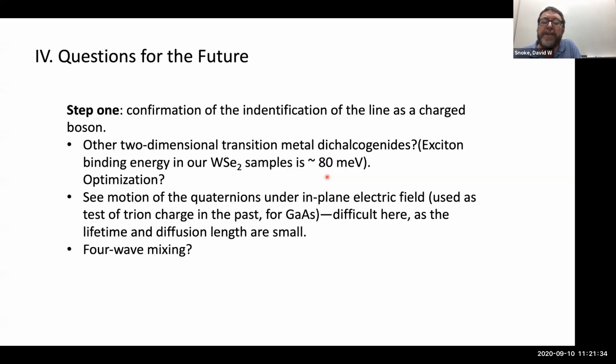A great experiment to do, which is a very difficult one, would be to apply an in-plane field and look at the luminescence to see whether it actually moves in response to an in-plane electric field. So you have a signature of where these things are, and they move. We have done initial trials on this just to look at the diffusion in the plane, and they don't diffuse very much at all. They have terrible diffusion, and that's pretty well agreed upon. A lot of people have concluded that. I'll have some comments to make about that.